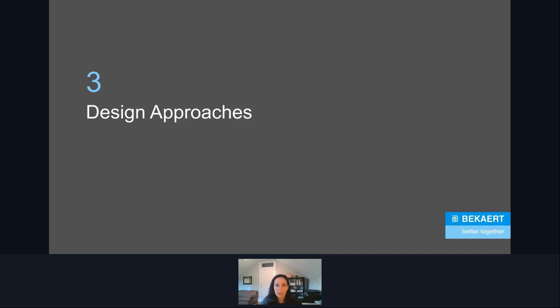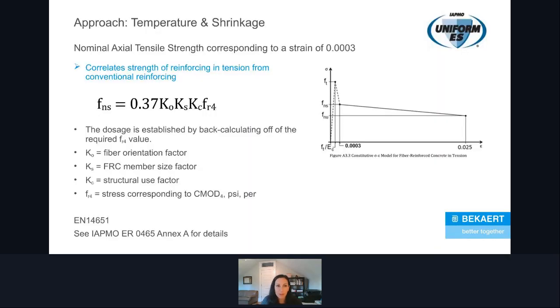So let's now transpose this into actual practice. What do we do with this information? So in design, one approach is just using steel fiber reinforcing for temperature and shrinkage, right? Crack control only. To do this, we go through a process to convert flexural performance, like we just discussed from the EN test, the EN 14651 test, into a corresponding axial tensile strength, because it's very hard to test concrete in tension. And so we go through a process of converting through flexural performance.